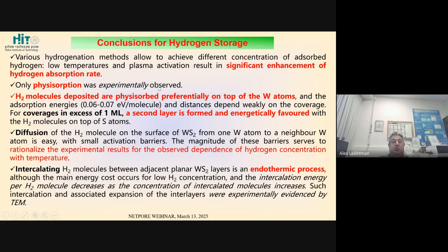Experimentally, we observed only physisorption. We performed Raman measurements and so on, and we never observed any chemisorption. So we never observed any bonding between hydrogen and sulfur, or hydrogen with tungsten. It's not possible. And there is, of course, also hydrogen diffusion, where low temperatures are beneficial, while the intercalation of hydrogen molecules is not favorable, but it occurs because of the defects mainly produced by plasma originally presented, and then we have this hydrogen inside the molecules, and then we also proved that it can be quite easily released at 40-50 degrees, but it's quite stable at room temperature.